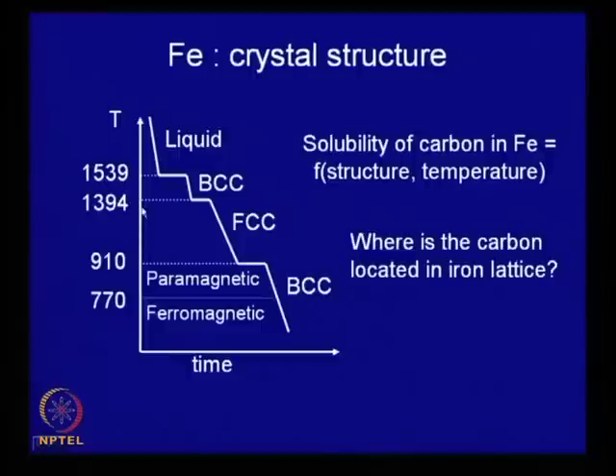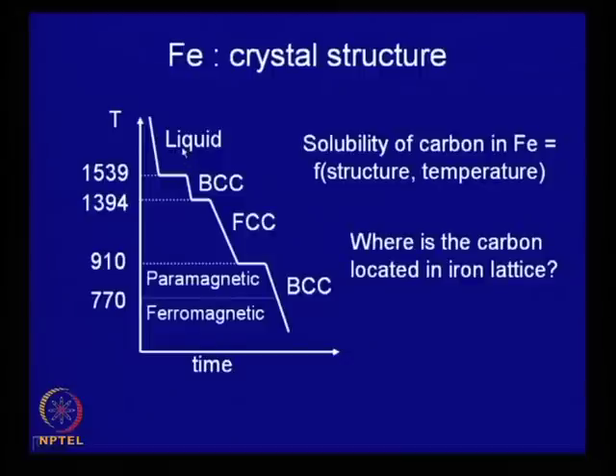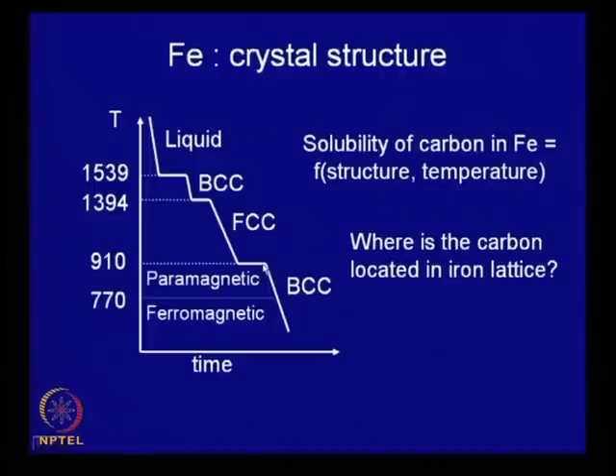If you take molten iron in a crucible, melt it, heat it to around 1550°C, and then let it cool very slowly while measuring the temperature — if you make a plot of temperature as a function of time — you will find in the cooling curve a number of steps. These steps represent equilibrium between the liquid and solid, and between two solid phases. So the transformation it goes through is: first the liquid solidifies into a crystalline structure, which is body-centered cubic.